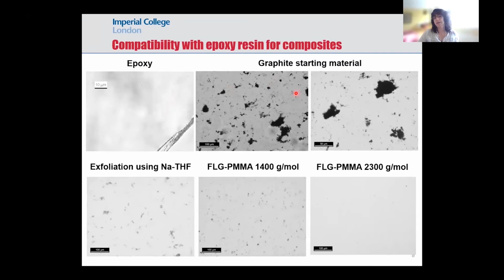So when we added the graphite starting material to epoxy, we observed the presence of big aggregates, meaning that it's not very compatible. And when we added exfoliated graphene, this aggregate became much smaller, and even more when we use the PMMA functionalized graphenes, and also with a higher molecular weight, we achieve a very good dispersibility in this epoxy resin, which will be good for further applications.